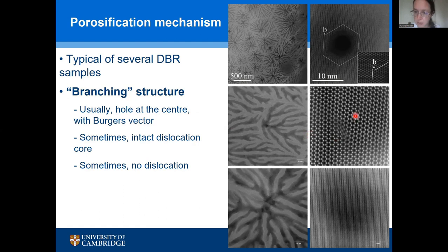So in this image here, you can see that in the perfect crystal, we've got these neat hexagonal rings of atoms. These are just the gallium atoms in the crystal. But if we look in this defected region, that neat hexagonal ring structure breaks down and we see larger and smaller rings of atoms. And that's because the bonding's all gone wrong because of introducing this extra half plane.